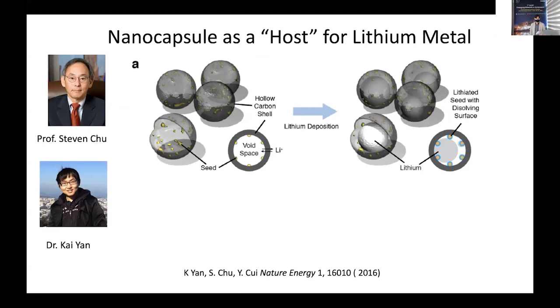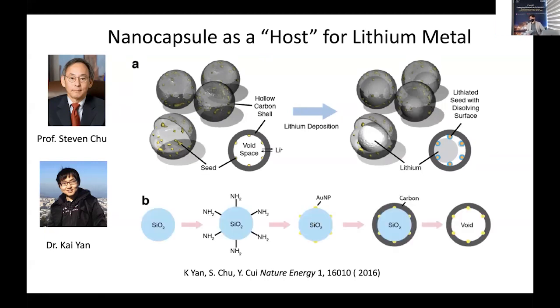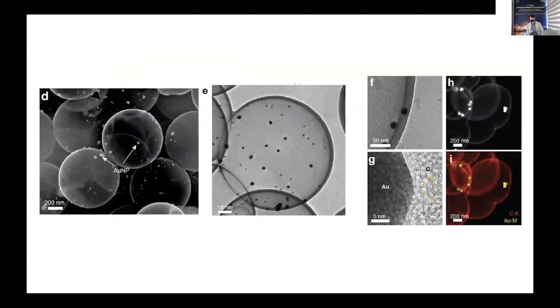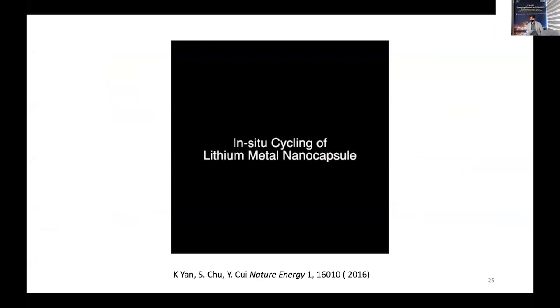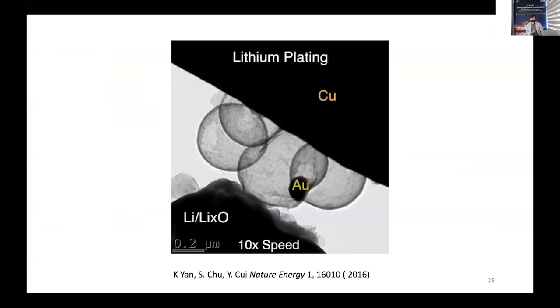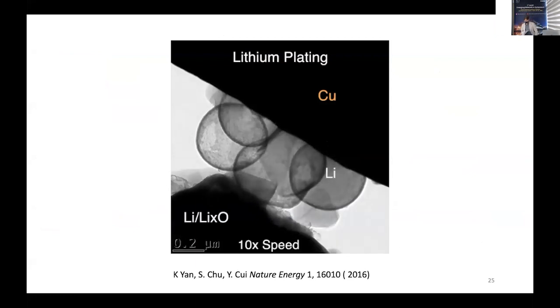Now we can control spatially where lithium will go, and this carbon shell will function as a solid electrolyte interface to isolate lithium from the organic electrolyte. And we made this structure, using TEM to confirm that. And in this in situ electrochemical cell cycling, we want to show you this gold nanoparticle now inside this hollow carbon sphere. We put lithium in, you can see lithium dissolve gold away. It has the ability, confirming our hypothesis based on the phase diagram.